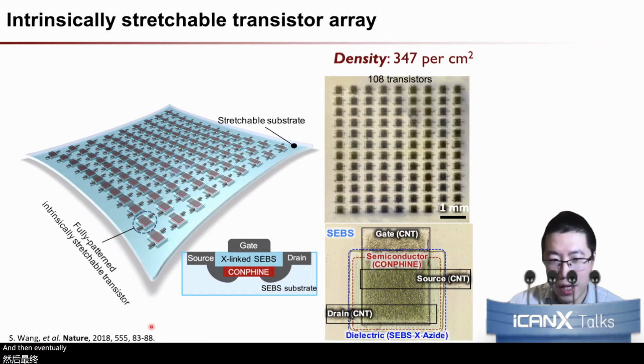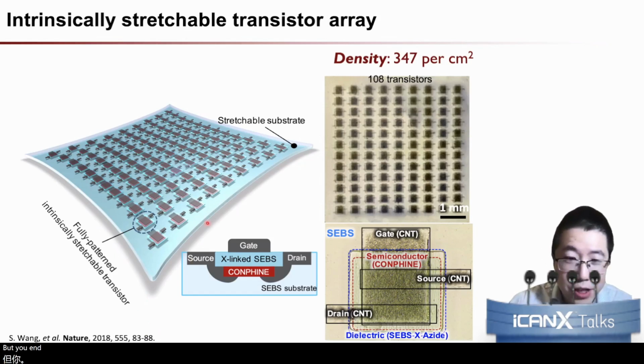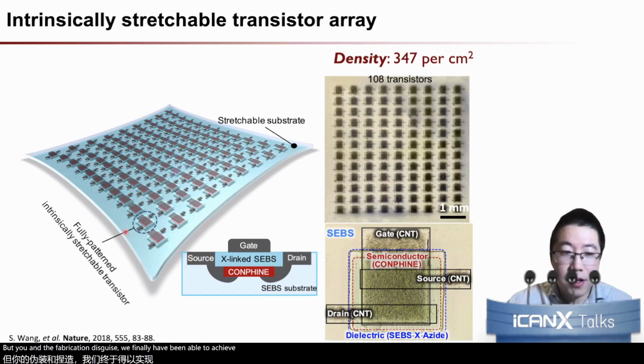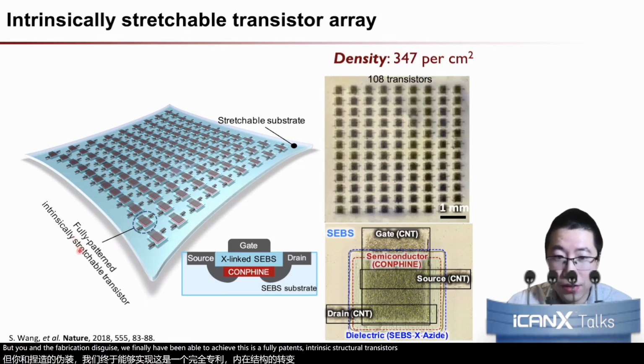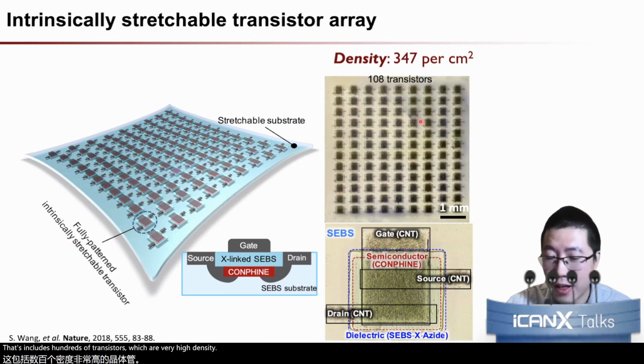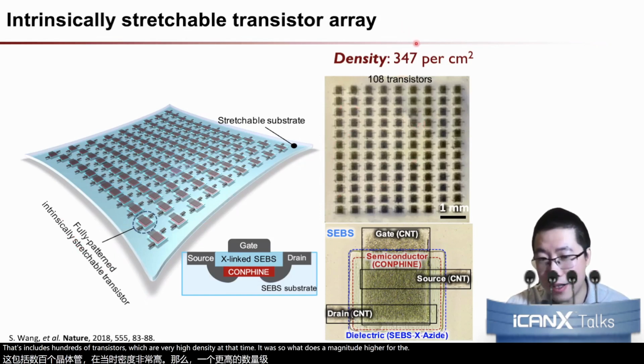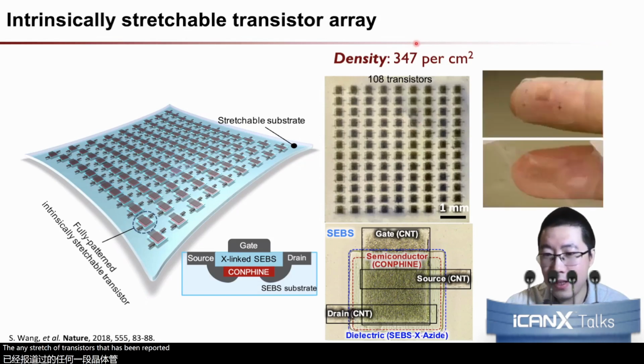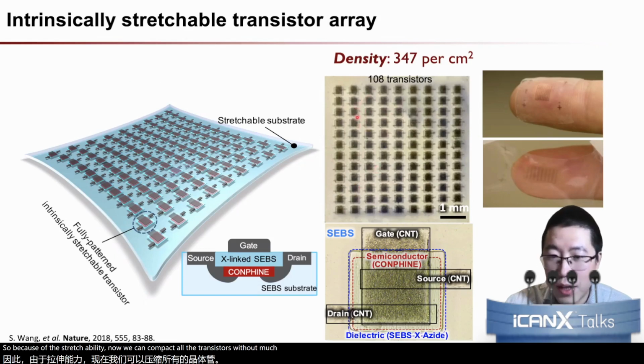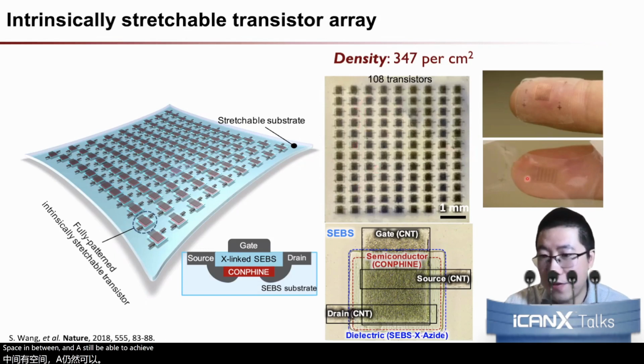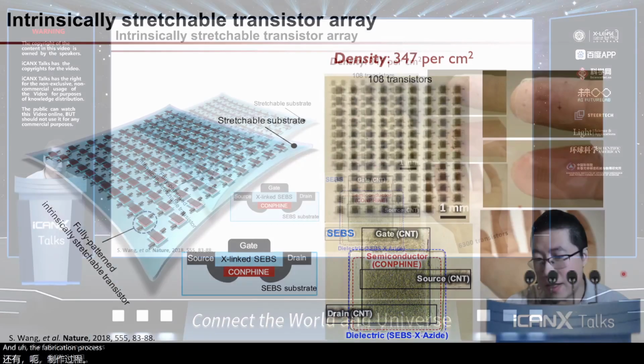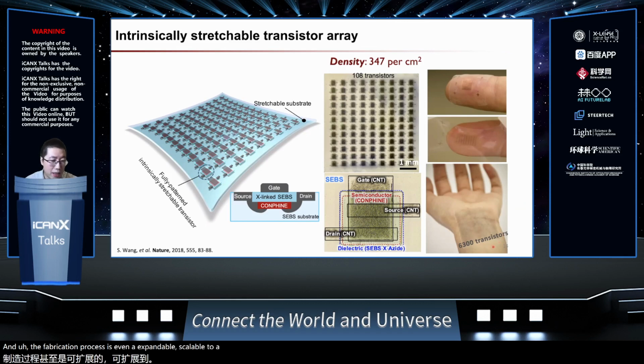And then eventually, combining all those new material and fabrication designs, we finally have been able to achieve this fully patterned intrinsically stretchable transistor array that includes hundreds of transistors with a very high density. At that time, it was 2 orders of magnitude higher in density than any stretchable transistors that had been reported. Because of the stretchability, we can compact all the transistors without much space in between, and still be able to achieve very good stretchability. And the fabrication process is even expandable, scalable to fabricate thousands of transistors in a single batch. And then this polymer-based sheet can be attached to the human body really conformably. You probably don't even feel it. That's at least what I have been feeling here.